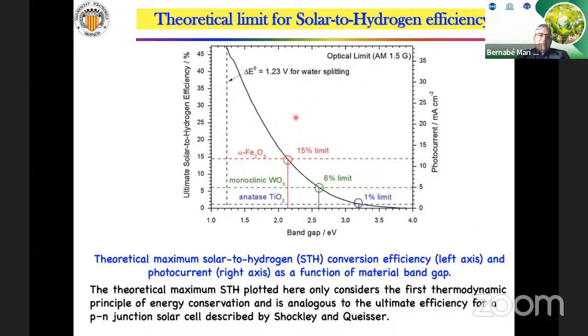Well, this slide represents the theoretical limit for solar to hydrogen efficiency. In some sense, this is similar to the Shockley-Queisser limit. So here it indicates the solar to hydrogen efficiency as a function of band gap. If you decrease the band gap, then you are able to afford more photons and to split more water molecules. The limit is 1.23 electron volts. But here you see for titanium oxide, the limit is 1%. If you reduce the band gap using tungsten oxide, 6%, and the limit for hematite is 15%.